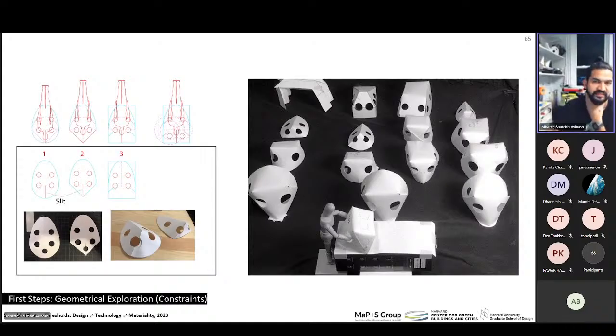Simple origami techniques were a good start and could easily be scaled up using thin sheets of PETG plastic. One drawback with origami was that it was accompanied by edges and creases. Hence, to omit the edges and get optical clarity, we started bending instead of folding. So, every well-defined edge became a smooth bent surface. The plastic needed to be thin enough to fold and bend, but stiff enough to keep shape and not wobble. The bending and locking also added a lot of structural stability to the forms.